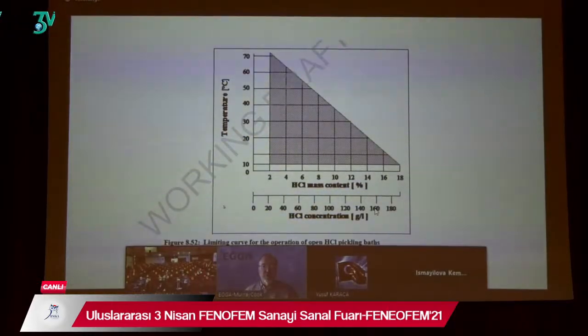I spoke about controlling the temperature and the concentration, so we have a very simple guide which combines the temperature of the hydrochloric acid with the concentration, and we know that if we stay in this grey area, so we stay, for example, normally below 14% concentration and below 20 degrees centigrade, we know that we have zero or insignificant emissions from the open tanks. So this is the method of control by temperature and concentration.